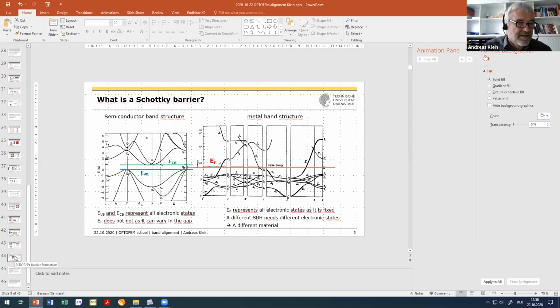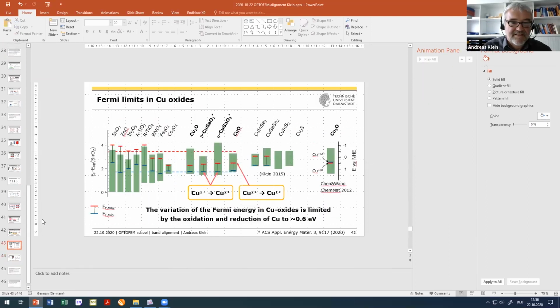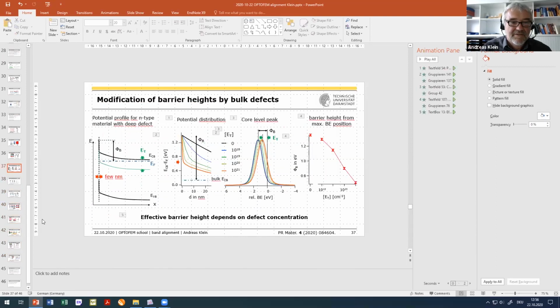And this can cause an effect which is very similar to what I have explained here at the very end. This one here. Then you have a trap level, and it makes a huge difference whether this trap level is occupied or not. That is something illumination can do. There are also effects related to what is called light soaking. This is in copper indium gallium diselenide solar cells. There are two possibilities to explain the light soaking. The one is copper diffusion, and the other is the filling of selenium vacancies by electrons.